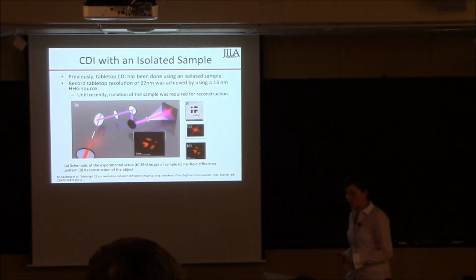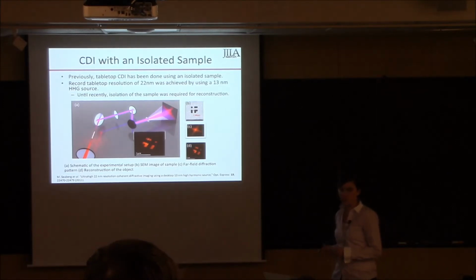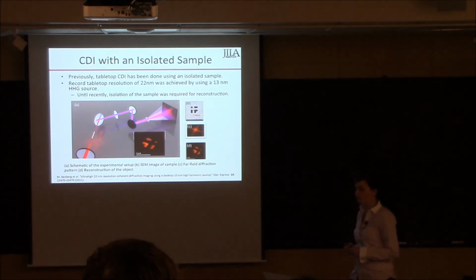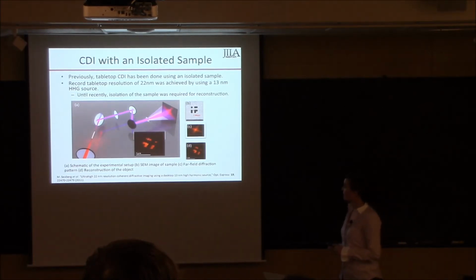So here are some experimental results from a few years ago when CDI was done in the group using an isolated sample. And we were able to push the resolution limit by achieving a record tabletop resolution of 22 nanometers using a 13 nanometer high harmonic generation source.